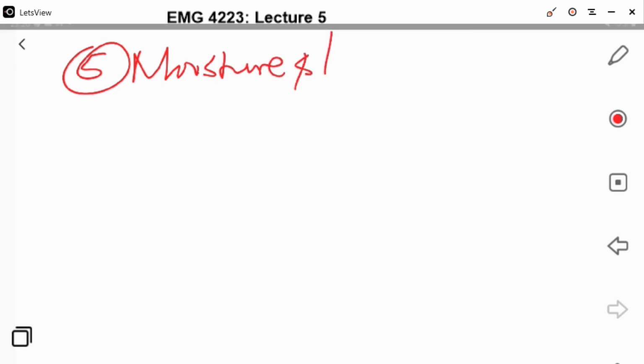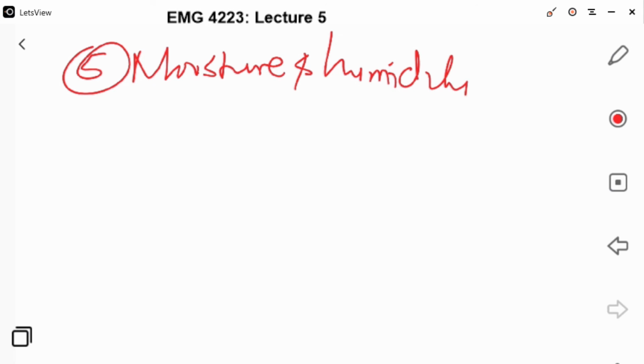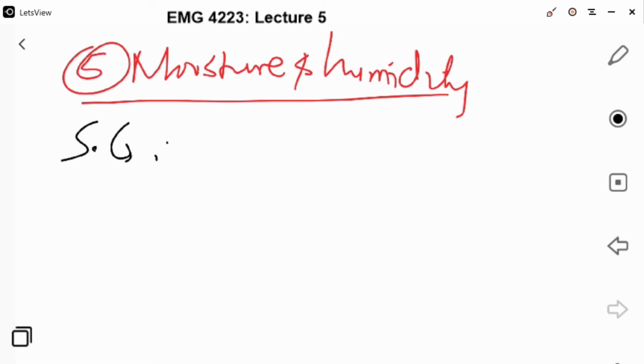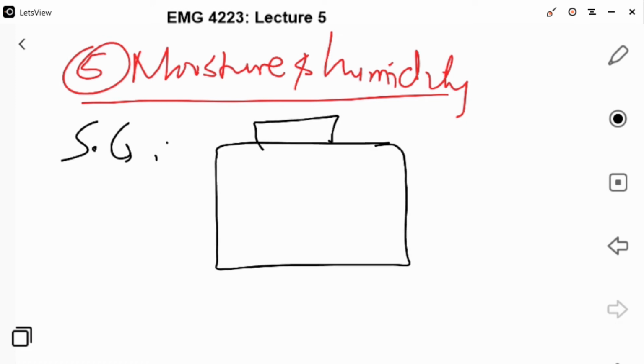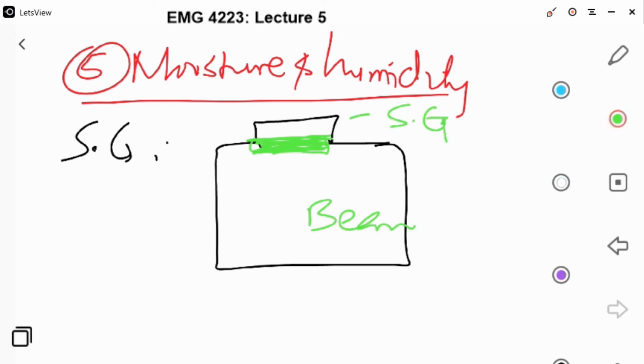Next, number 5, is moisture and humidity. These two parameters affect the strain gauge reading in the sense that if moisture comes into contact, so if this is the adhesion between the strain gauge and the sample, this is a beam, this is a strain gauge, if the moisture penetrates the adhesive, that adhesive is going to expand and therefore affect the reading.